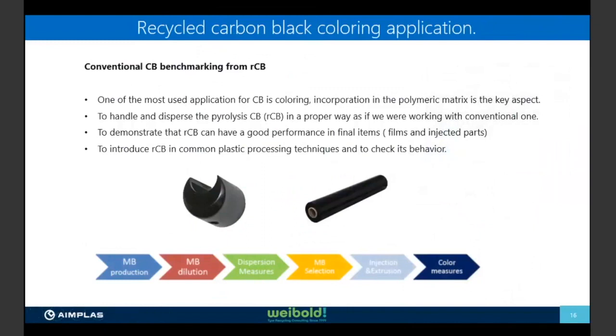Okay, and the structure of the work that we did was the one that you have here in the slide. You know that most of the time when you are working with plastics or with polymers, you need to add additives in the form of masterbatch, which is a concentrate that can have additives, pigments, and so on. In this case, we have carbon black. Afterwards, we do a dilution in injection molding and extrusion. And we make dispersion measurements. I have skipped this because we don't have so much time. But anyway, those dispersion measurements are very important for us. I always recommend making dispersion measurements of anything that you are mixing. I don't care if you are mixing plastics, thermosets, or if you are mixing rubber with anything.